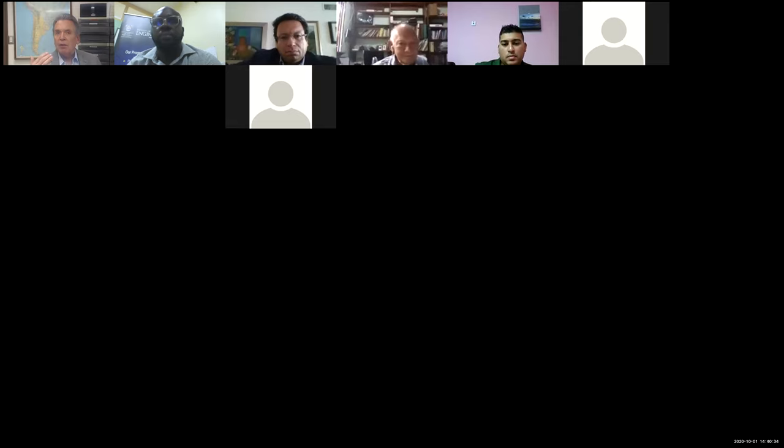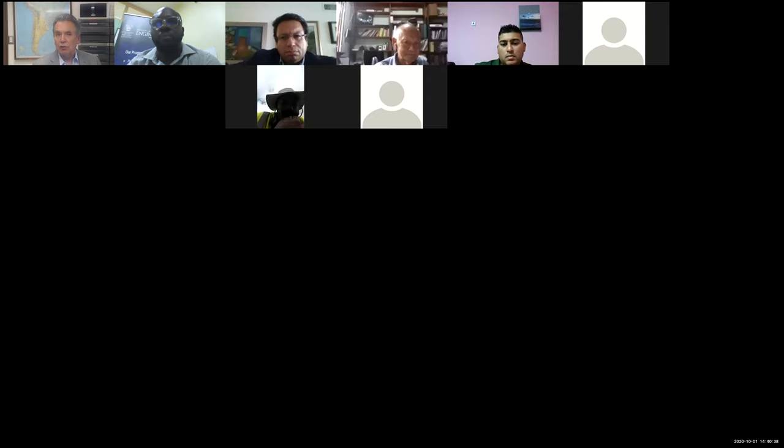But in summary, these BSM layers have surprised us under soaked conditions. They have performed very well because they capture the fines. So if water ingresses, they actually have a better behavior under, let's say, extreme soak conditions, which we would have in the Caribbean with huge rainfalls and things like that, compared to standard granular materials.